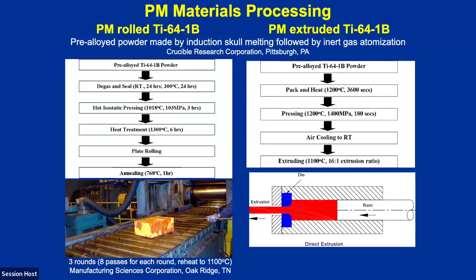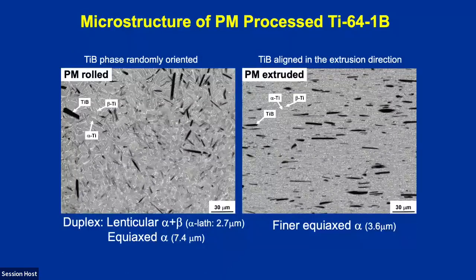And here's a picture of the microstructures. Again, on the left is the 641 boron with the rolled, and this is on the right. And it was extruded in this direction and rolled in this direction. But you can see that there's a strong difference in the microstructures.